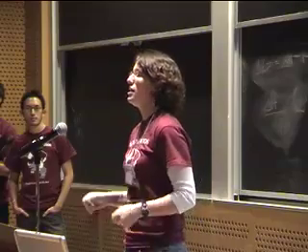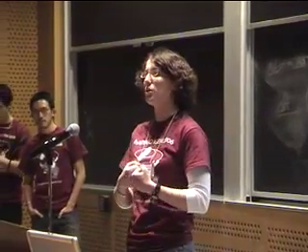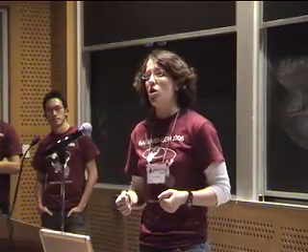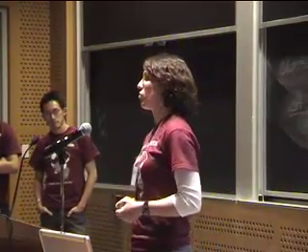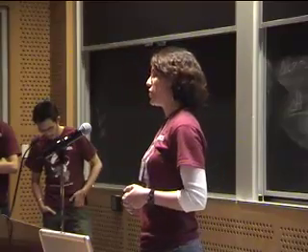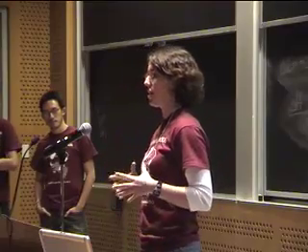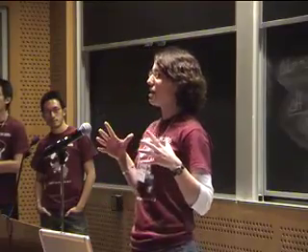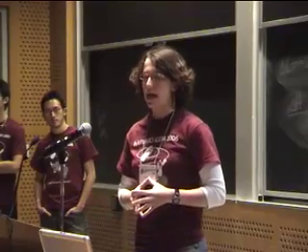So how does this work to build a larger structure? We've seen two double helices put together. How can we put a lot of them together how we want? Well, the method we've used has been pioneered by Ned Seeman at NYU, Paul Rothemund at Caltech, and here William Shih at Harvard, among others, and it's called scaffolded origami. What it means is you take a large single strand of DNA. What we usually use is about a 7,000 base pair long piece of viral genome, and we add to it